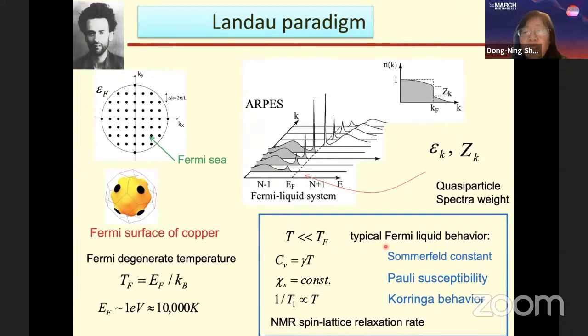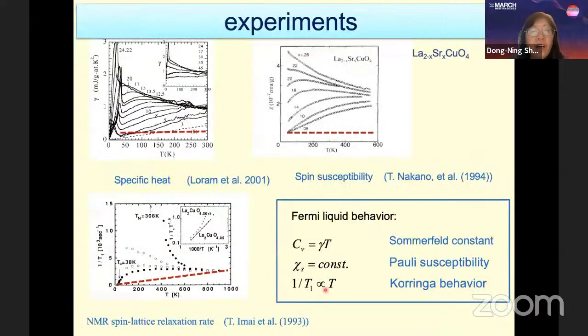If they are Fermi-liquids, with pairing of quasi-particles at the Fermi surface, then those quantities should follow definite behavior, like specific heat having a linear T behavior, and spin susceptibility being constant. However, experimental results indicate that none of those behaviors are observed.